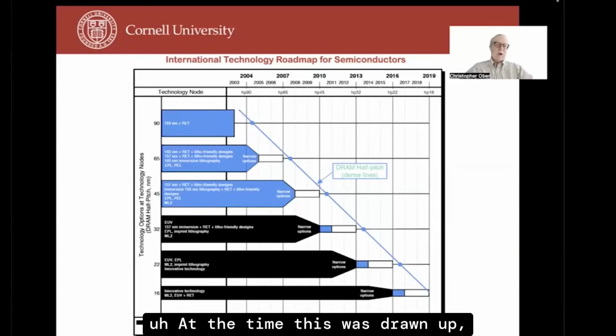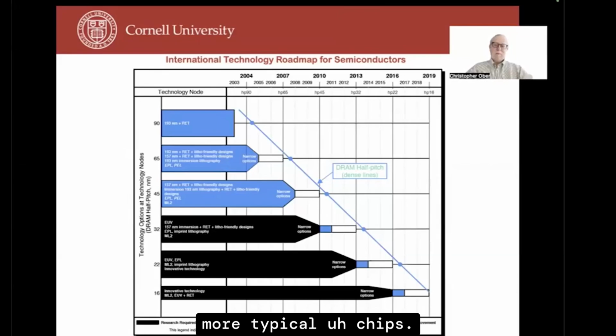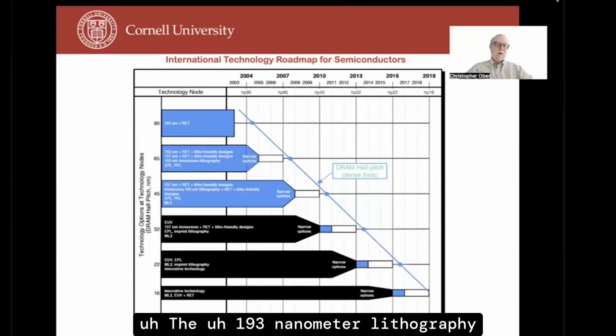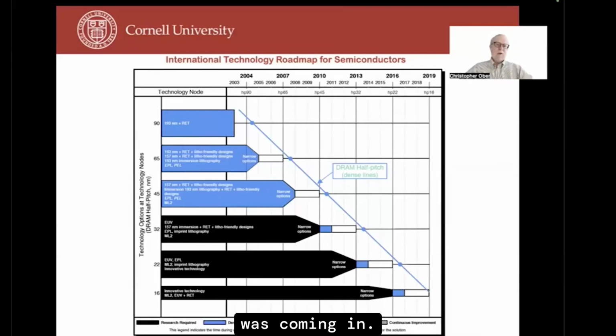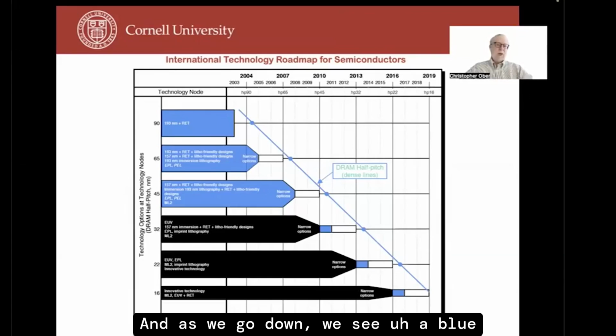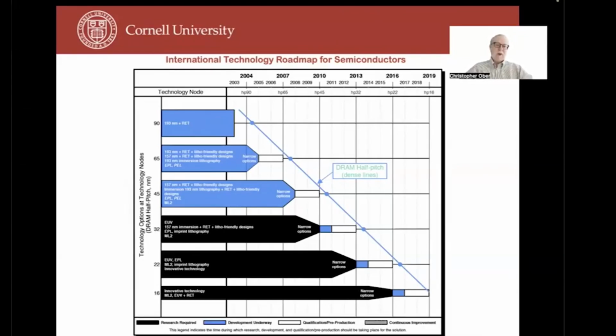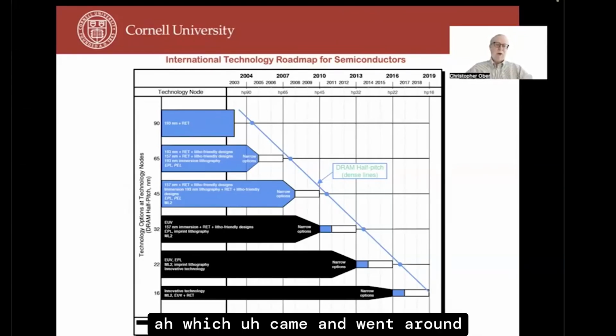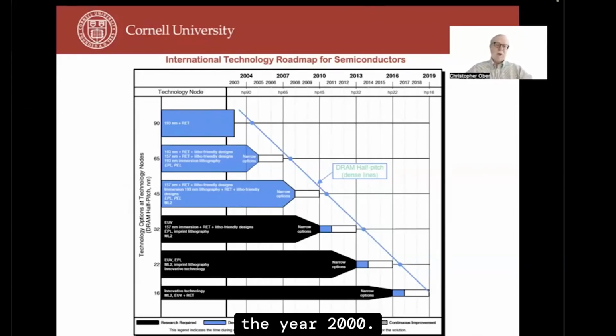At the time this was drawn up, 248 nanometer lithography, use of ultraviolet light at 248 nanometers, was a big chunk of the more typical chips. The 193 nanometer lithography was coming in, and as we go down, we see a blue box, the lowermost blue box, showing 157 nanometer lithography, which came and went around the year 2000.